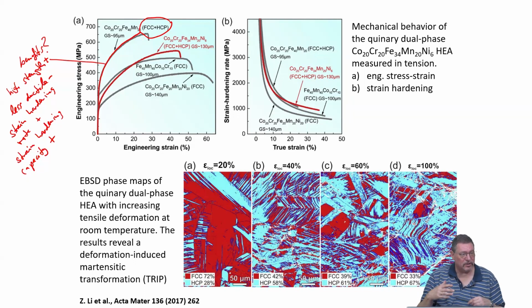Yes, the transformation is driven by the mechanical energy, so it's transformed into a microstructure feature. Also, following dislocations have a problem passing the phase boundary between austenite and martensite, right? So this is also helping them and increasing the strain hardening capacity of the material.